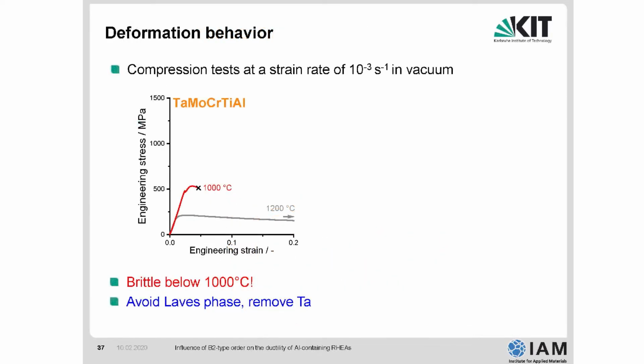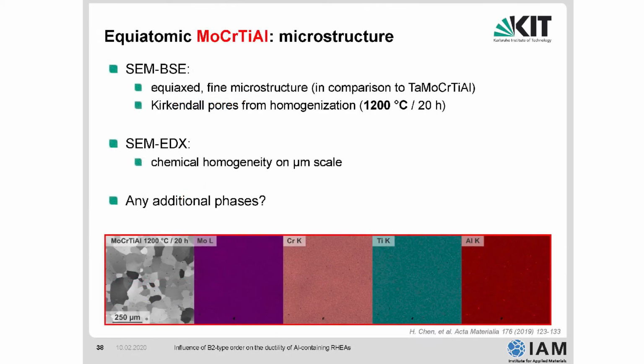And now, what is the consequence on the deformation behavior? Here you see stress-strain curves. Everybody should be familiar with that. Stress-strain curves at various temperatures. You see, below 1000 degrees Celsius, you cannot even take a stress-strain curve because the material fails elastically. So it's totally brittle below 1000 degrees C. The reason, we guess, is that we have to avoid this Laves phase at the grain boundaries. And I will show you briefly in the last 5 minutes how we tried to accomplish it.